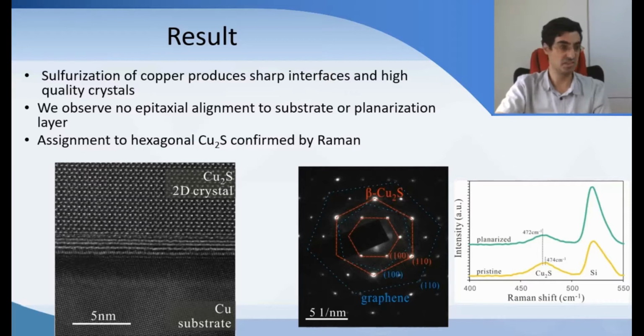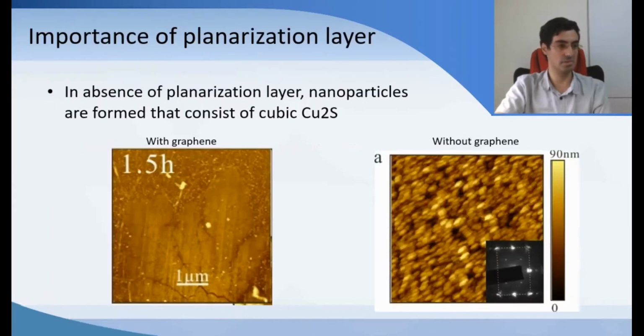The first one is it's changing its morphology. It is making the copper sulfide flat, as opposed to having clusters on the just sulfurized copper surface. The other thing is that if you use an untreated surface of copper without graphene, you get cubic phase copper sulfide, whereas you get a hexagonal phase copper sulfide with the graphene superlayer. And so that means that the growth morphology is completely different.